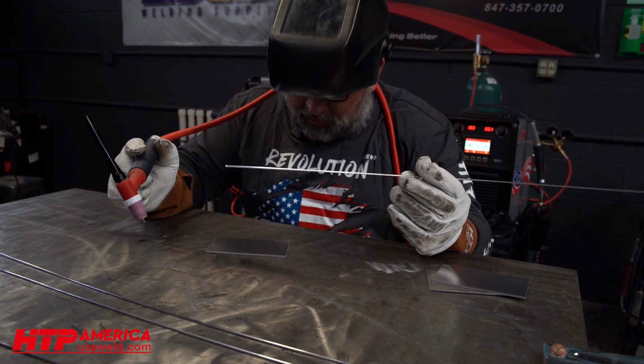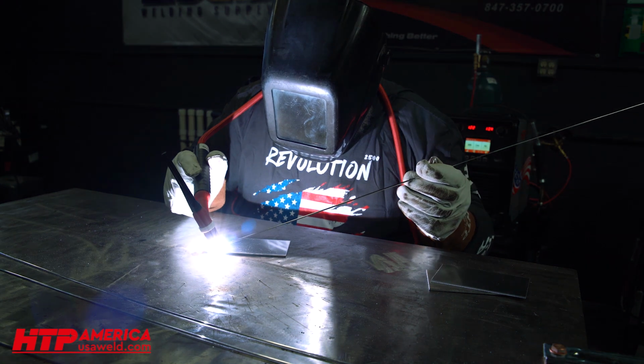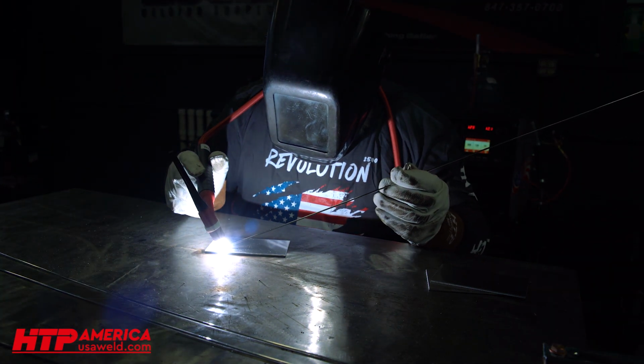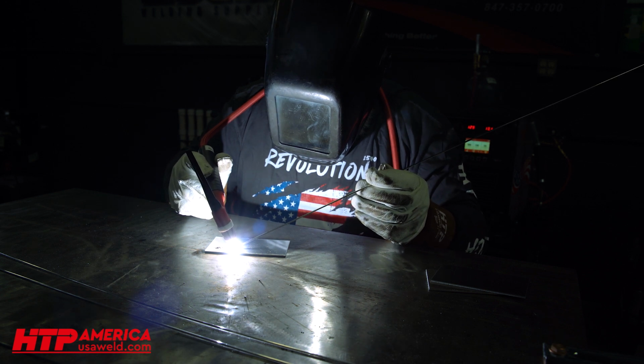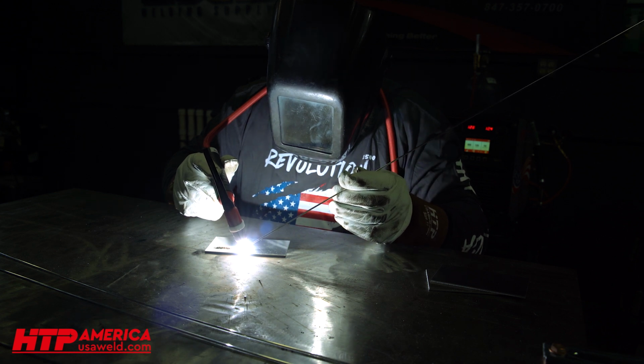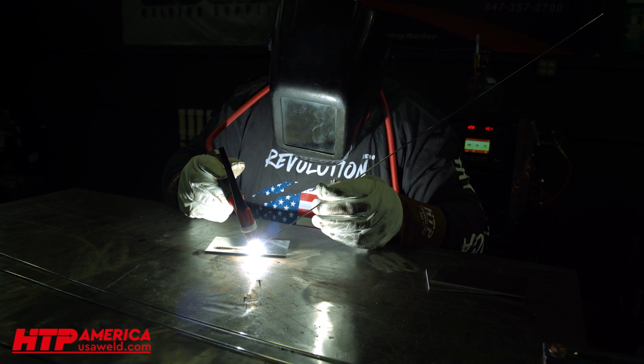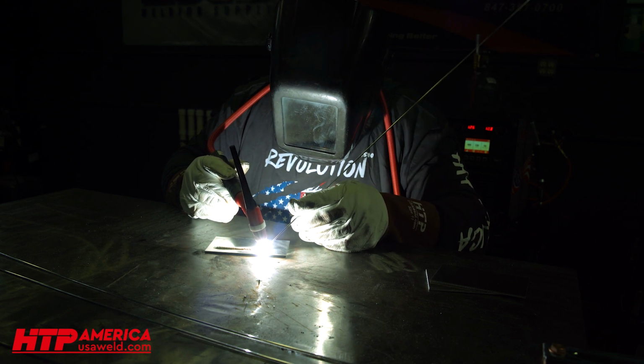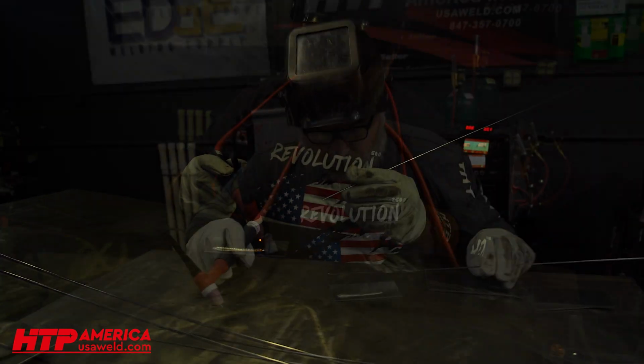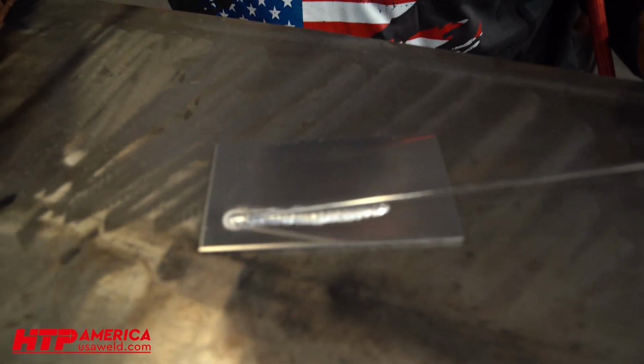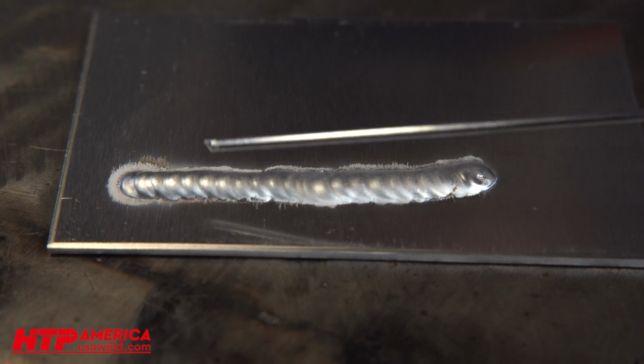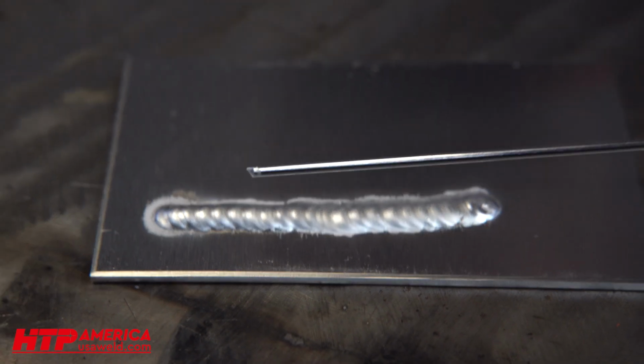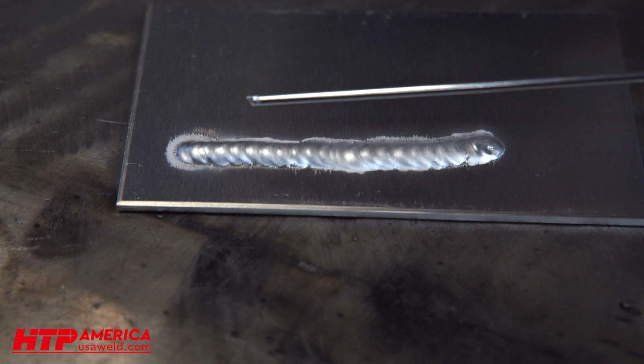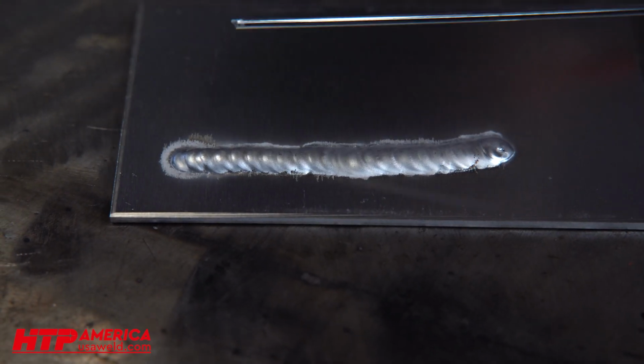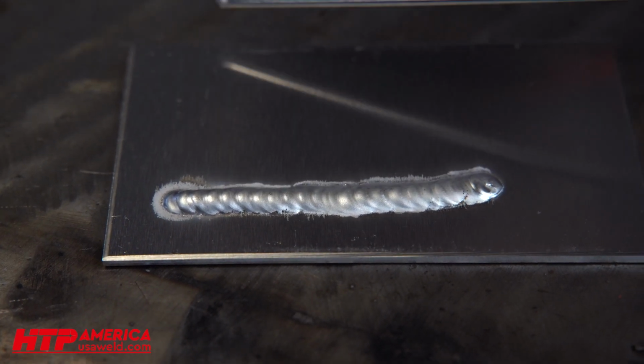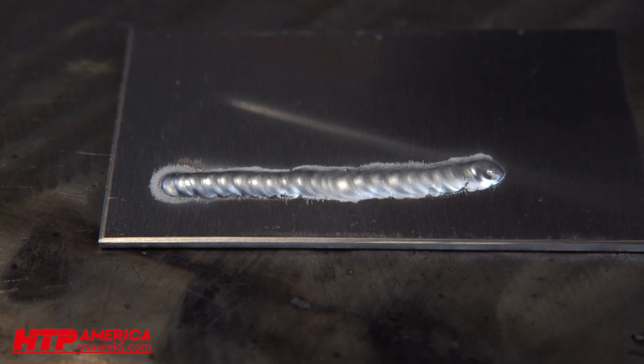Okay, next one, 5356, 3/32. So with this rod, what you can see is the ripples are a little bit more pronounced. It freezes a little bit faster with the magnesium in there. You should have been able to observe that the arc had a greenish tint to it. It's not as silvery and shiny as the 4043. Overall, a decent weld.